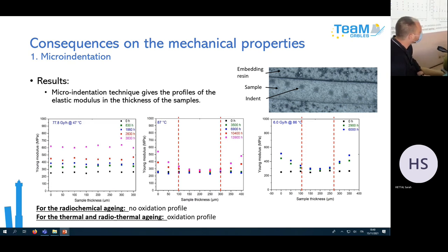experiments. I don't know if it's possible to probe the cross-linking density with the Young's modulus at room temperature. Yeah, at room temperature. Because if you do so, the greatest contribution would be the crystal, actually, inside the material. So you would have to melt the crystal, have a molten state, an elastomer, and then do a tensile test. We haven't done that. But that could be an idea to probe the cross-linking density, absolutely, yes.